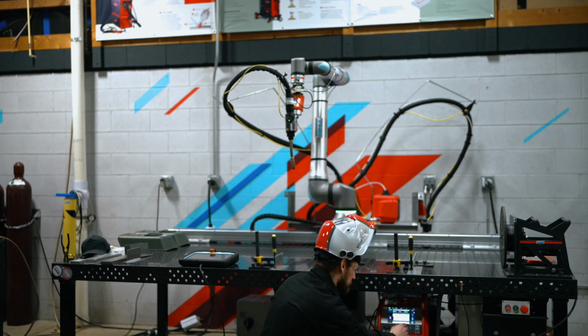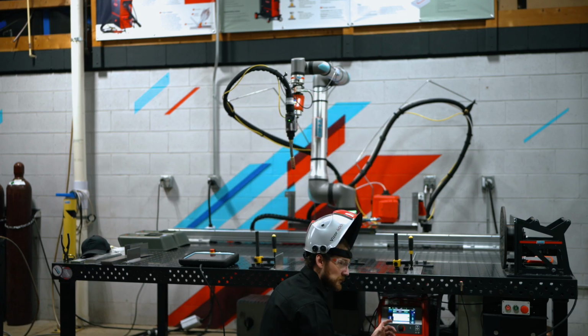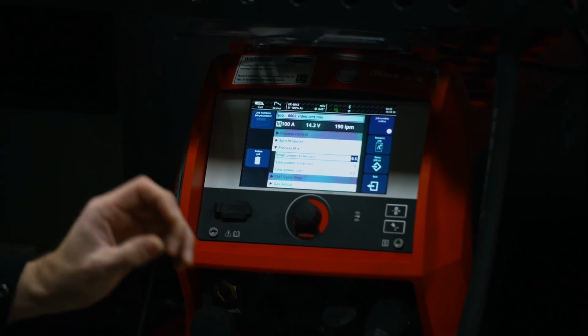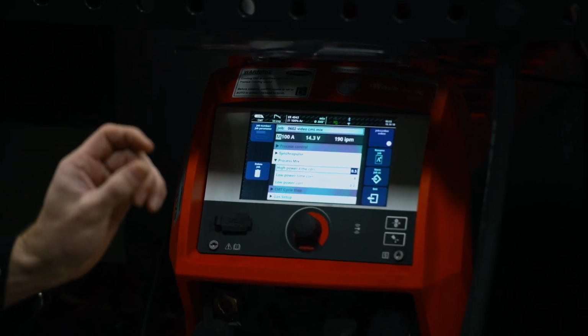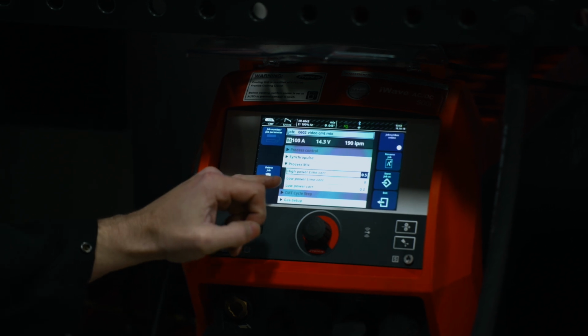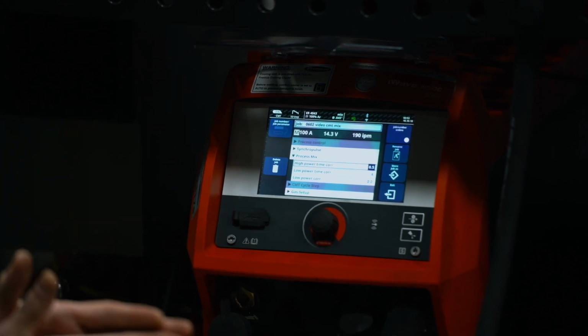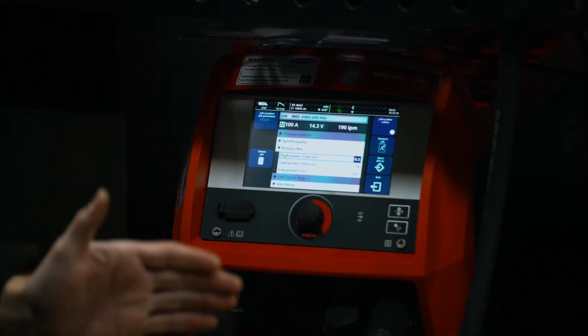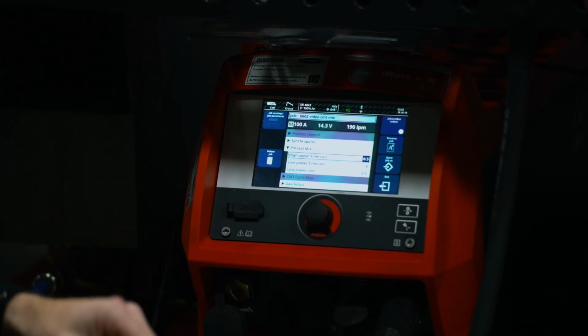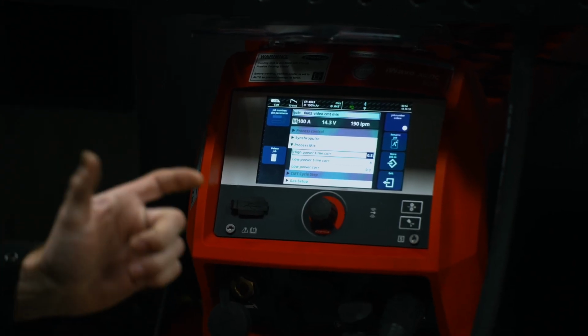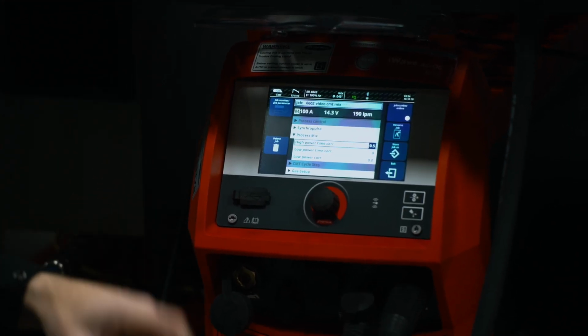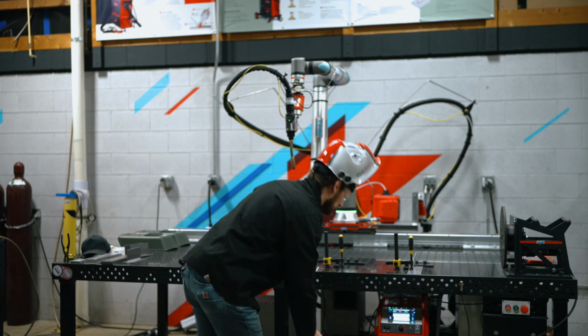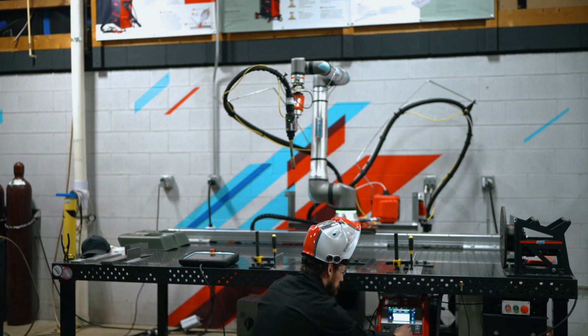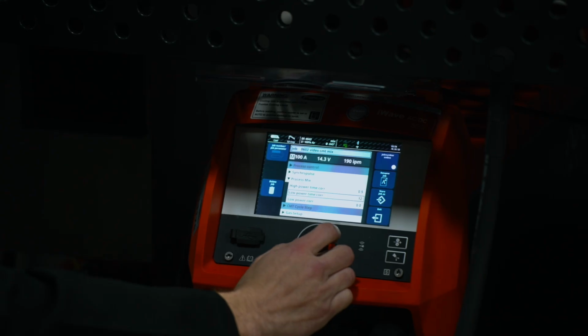you have the controllability with the Fronius equipment to control the high side and the low side of that mix process. Going up on the high side will give you a larger dime appearance, and then going up on your low power time correction will increase that spacing or the cool side of the process, allowing you to get an elongated stack of dimes appearance. So on this example, we're going to go up to say 12 on our low side.